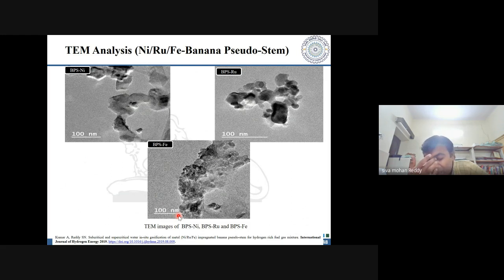So the particle size was found to be typically in the range of around 40 nanometers for nickel, around 50 to 55 nanometers for ruthenium most probably, and around 30 to 45 nanometers for iron. Okay, so from the TEM analysis of this metal impregnated biomass, we can convey that the metals embedded in the biomass matrix are in the nano range.